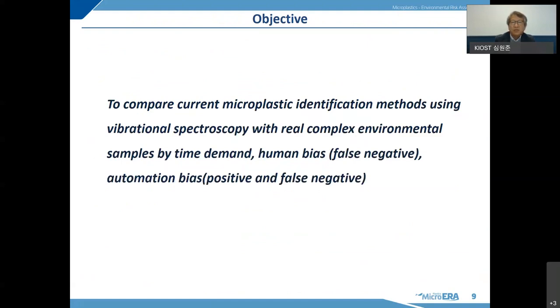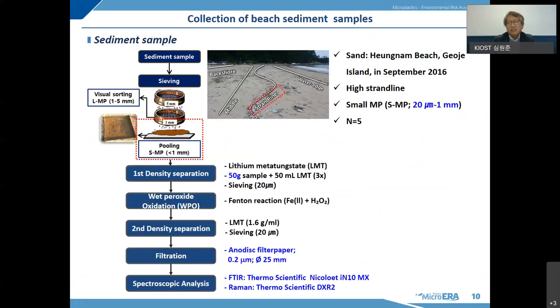In my study, we tried to compare current microplastic identification methods using vibrational spectroscopy with real complex environmental samples, and their performance was evaluated with the four criteria I mentioned. For this study, we collected beach sediment samples from the high strand line on a beach in Korea. After homogenization of the sand samples, we prepared five replicate samples. Microplastic particles were extracted from the sediment using density separation with lithium metatungstate, and interfering organic material was removed by wet oxidation, followed by a second separation with lithium metatungstate solution. Finally, the supernatant was filtered with an anodisc filter paper.